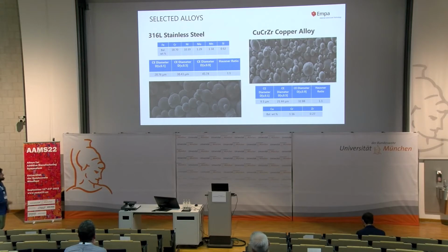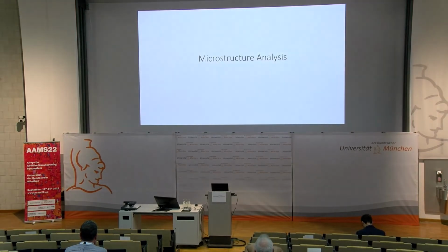We know that 316L stainless steel is one of the most characteristic representative grades of austenitic stainless steel, with possible appearance of a small amount of ferrite based on the scanning strategy. And this copper chromium zirconium alloy has a low amount of chromium and zirconium, no more than 2%, and we expect to have the copper matrix, and based on the scanning strategy, we may have a percentage of some copper zirconium precipitates or segregated chromium.